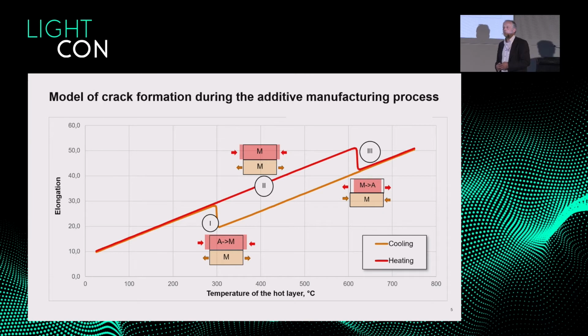So starting the design of new materials or new steels for additive manufacturing, we are working with a very simple model. This is the measured elongation over the temperature, and this is valid if you have a process of rapid heating and rapid cooling, which is standard for additive manufacturing, if you produce your part layer by layer. You start with high temperature because you heat a small spot. You have a big amount of processed material. You cool very fast, and then you have a phase transition at low temperature. Normally, this is a martensite. And in this case, you have a slightly abnormal behavior of this material. You cool it down, and it increases in size.